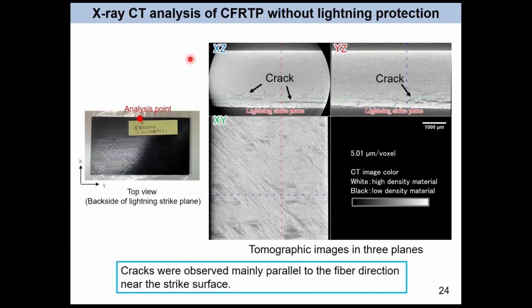This result is the original CFRTP without lightning protection. This side is the lightning strike plane, and we can see the crack propagates in parallel to the surface, so along the carbon fiber direction. This is the XZ plane, also the YZ plane, and this darker color area is the damaged area. So some lightning protection system is necessary for CFRTP.